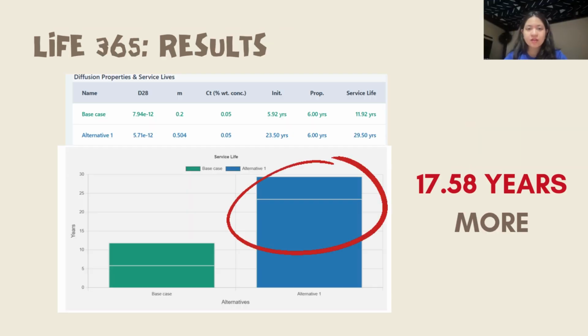This slide presents the total service life prediction for both the base and alternative mix designs using a Life-365 model. For the base case, it predicted a service life of up to 11.92 years. On the other hand, the alternative case significantly extends the service life to 29.50 years.